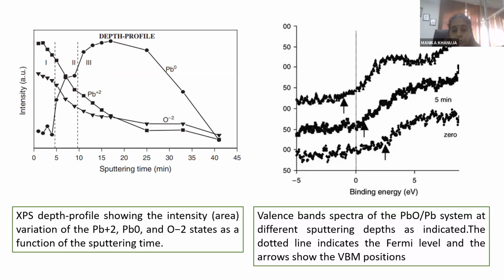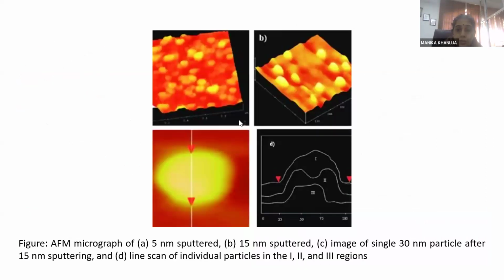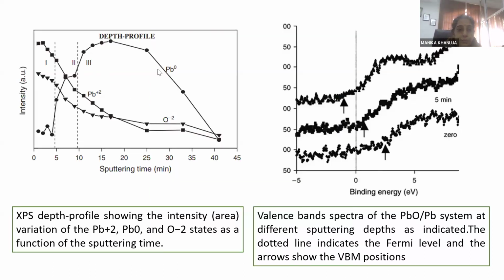When you see the egg yolk part, and in this line scan also, for this 30 nanometer first region, you see the line scan is a smooth hemispherical one. When you sputtered it, you basically punctured it. In between you can see this hump. Once this hump is removed, the third region is when the core region is visible. So this is how the XPS, AFM, and transmission results are correlated. This paper, maybe right now you have grasped only partly, not 100%. I'm not able to convey it fully, but later on with the paper you can see it further.